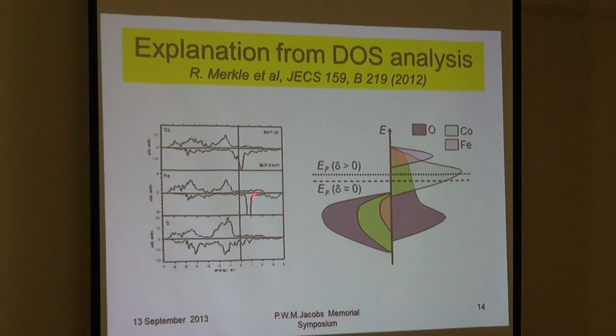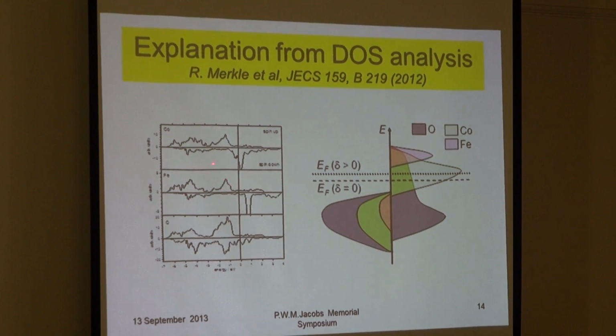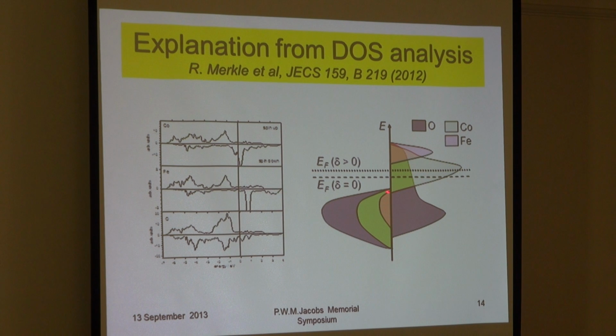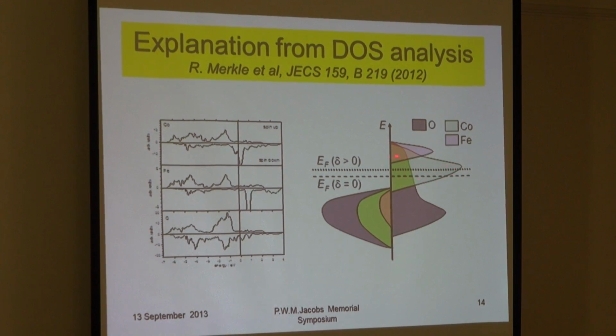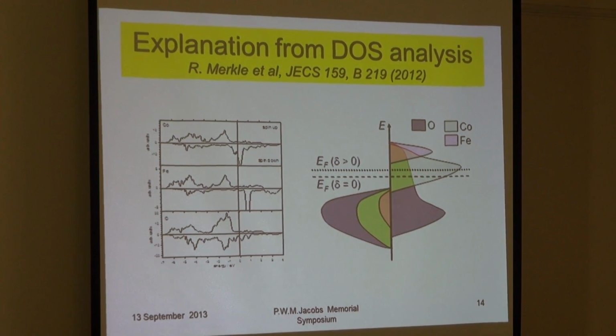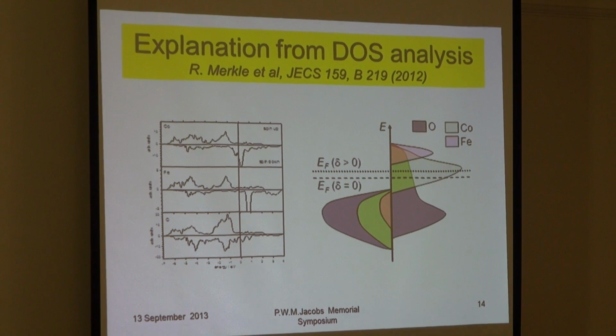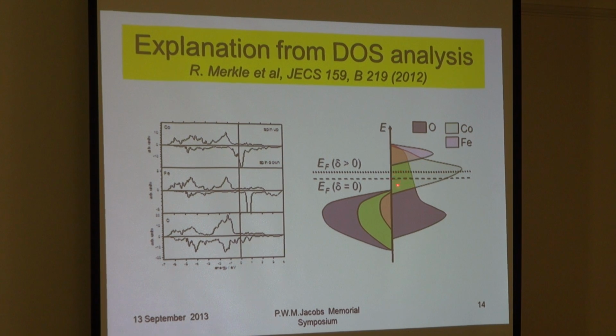And why cobaltite is so efficient could be understood from the analysis of density of states. Essentially, for iron, we have a high spin configuration, and for cobalt it's intermediate spin. And if you look at this diagram, it's alpha and beta spins. So essentially, it means that for beta electrons, this peak of cobalt is overlapping with the Fermi level. And for iron, it lies much lower in energy. So when you create an oxygen vacancy and electrons go to the nearest B-type cation, cobalt easily accepts electrons, so the Fermi level changes a little bit, and most of the electrons easily go to cobalt, but not to iron, because to get to iron it needs much higher energy. So it's a very simple chemical understanding why cobaltites are more efficient.